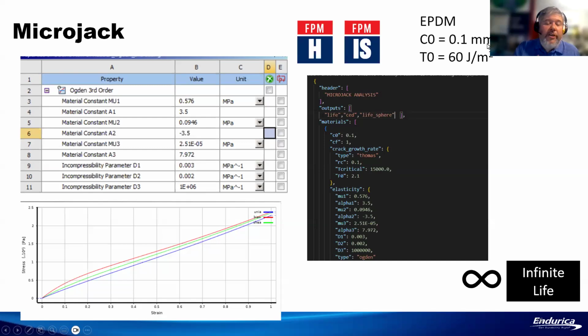And I should mention, when you're using Endurica, it always assumes that your material contains microscopic cracks. And one of the important inputs for the material characterization is, what is the initial size of those cracks? We can measure that experimentally, or you can make an assumption about that. Typically, they're in the range from 20 to 100 microns. So you can see in this case, we've used a sort of a conservative assumption of a tenth of a millimeter.